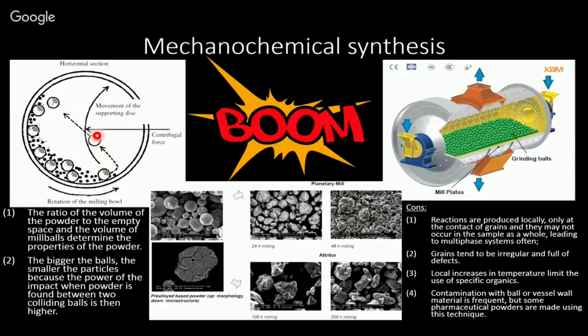So one of them is the contamination issue, because you cannot avoid it. All these balls and the vessel walls are always going to contaminate the particles to some extent. However, there's a solution to minimize that, and particularly if you use tungsten carbide balls, you can minimize the contamination. So be aware of that. Tungsten carbide is a very, very good solution for this, and that's what is being used in the pharmaceutical industry, actually.